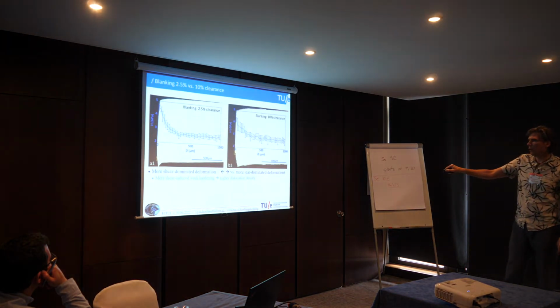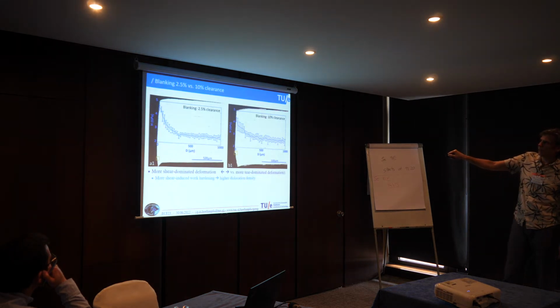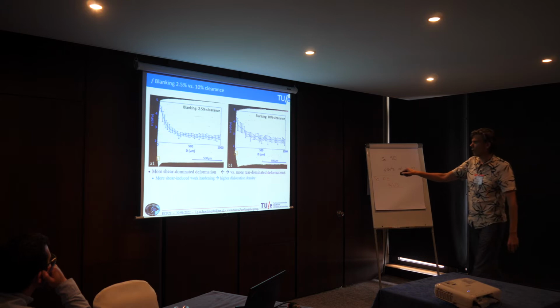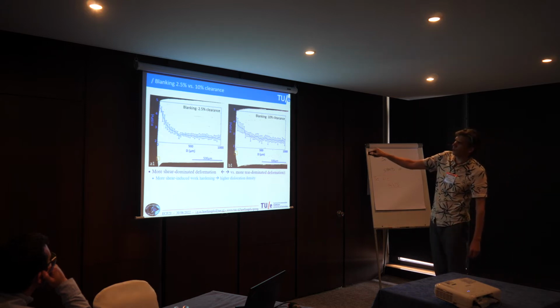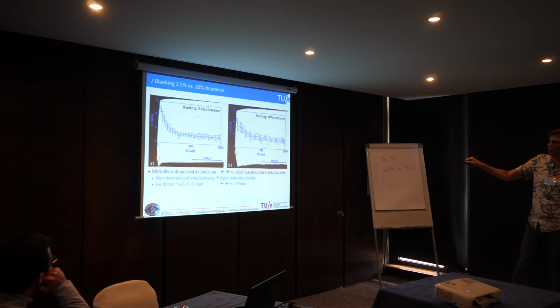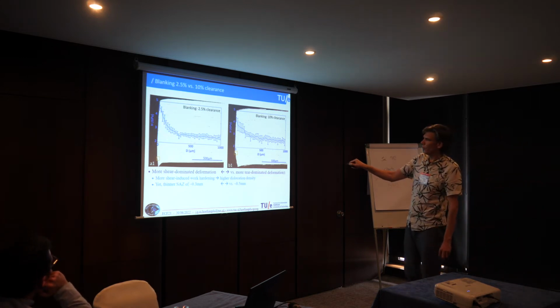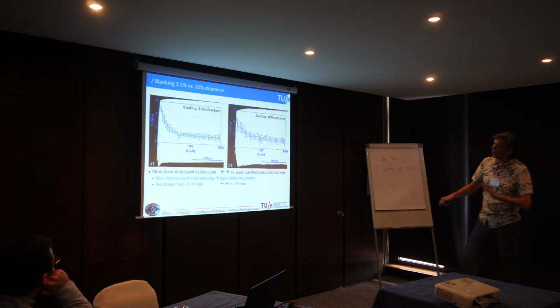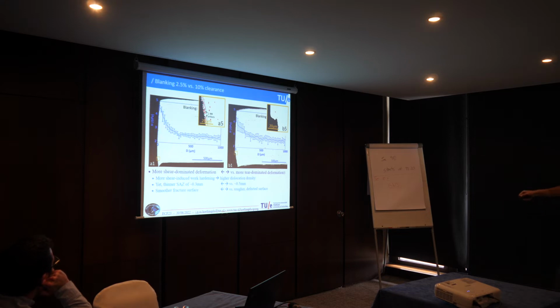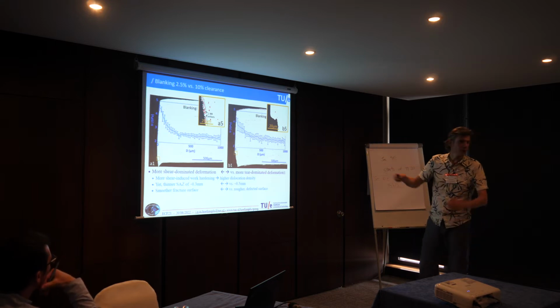We also see more shear induced work hardening here. That leads actually to a higher hardness and a higher dislocation density in this case. Yet in the 2.5% clearance we get a thinner shear affected zone, 0.3 millimeters versus 0.5. So this is all actually a bit what we expected. And then this corresponds to, because this is more shear dominated, we get a cleaner fracture surface.